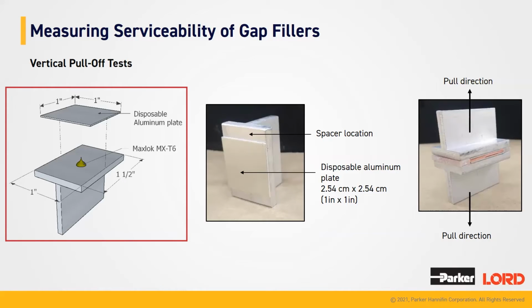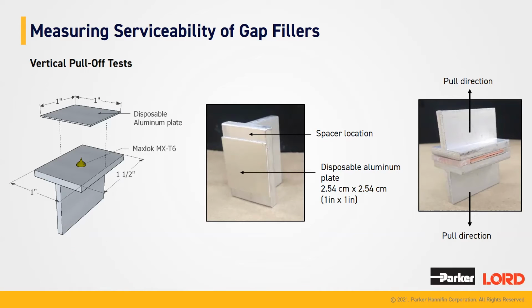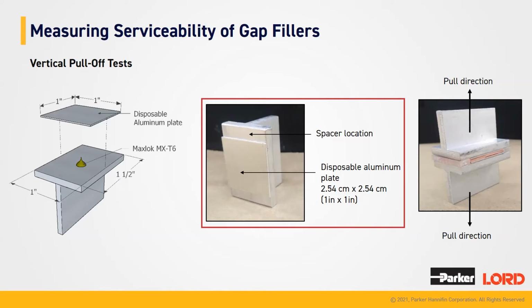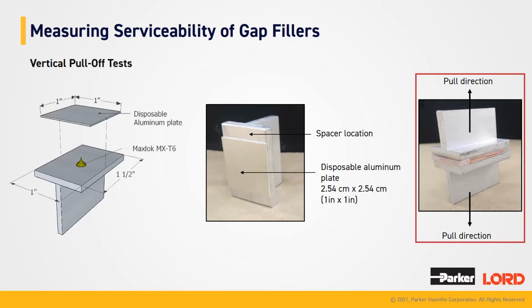As you can see on the picture on the left, we have a T-bar, and then we adhere a disposable aluminum plate to this T-bar using one of our structural adhesives, Maxlok MX-T6, which is an acrylic structural adhesive. Then you can see we end up with what's pictured in the middle. This allows us to have space on either side of that disposable aluminum plate, so we can add spacers to dictate bond line thickness.